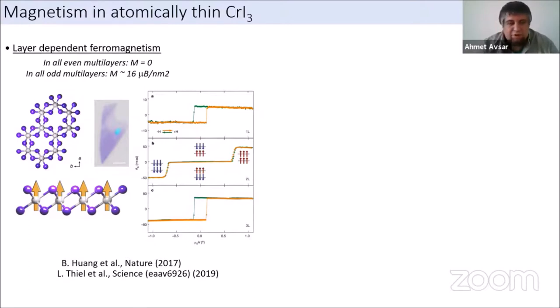It was then shown that all the materials with an even number of layers show zero magnetization at zero field. Once you apply a magnetic field above the coercive field, you can change the magnetization direction of one of the layers, and it becomes fully spin polarized again, as you see here. So these materials give us the opportunity to have layer-dependent magnetism, which is not possible with conventionally grown materials.